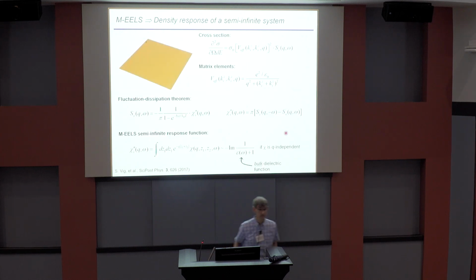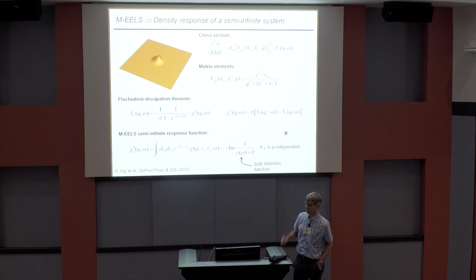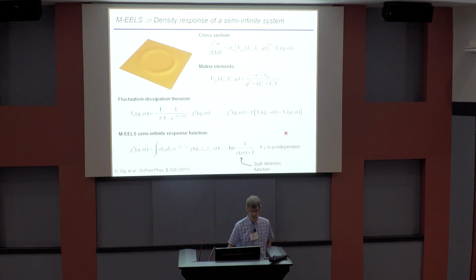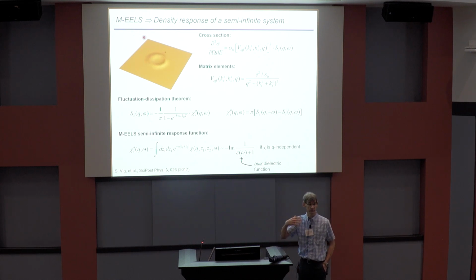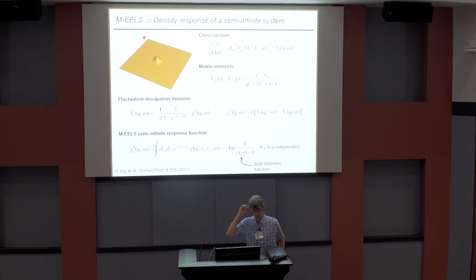So that's what we've been trying to find out. The technique we've been using is EELS. We've developed a new brand of surface reflection EELS. We've been calling it M-EELS just to emphasize the fact that it's fully momentum resolved, the same way you get momentum resolution in triple axis neutron scattering. We do it using eucentric goniometers. And basically what you do is you shoot an electron at a surface. The surface has to be prepared in the same way you would do for photoemission. And then you measure the scattering cross-section. The cross-section is some matrix elements, which you can write out analytically in a reasonable approximation, times the density correlation function of the surface. So that's just the spectrum of fluctuations.